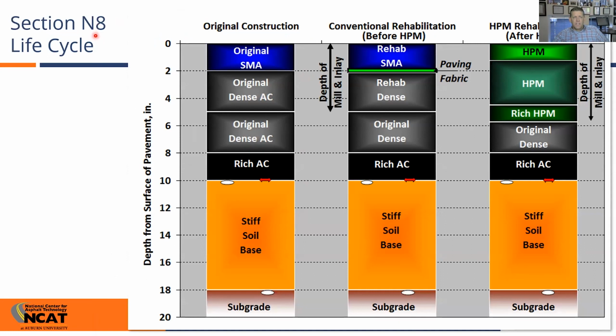So this is looking just at section N8. We had the original construction, and after the first 10 million ESALs, we saw extensive cracking in the section. And in discussions with the Oklahoma DOT, they asked us to do what they normally would do in this situation, which would be to mill off. And in this case, they asked us to mill off about half the depth and then put back in the same material that we originally had. We'll call that the rehab dense layer, put in a paving fabric, and then SMA on top of it. So essentially rebuild about half the section and add in a paving fabric.